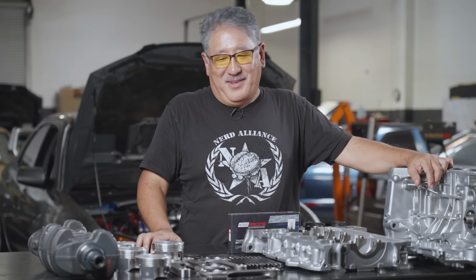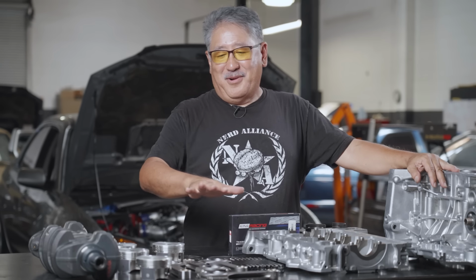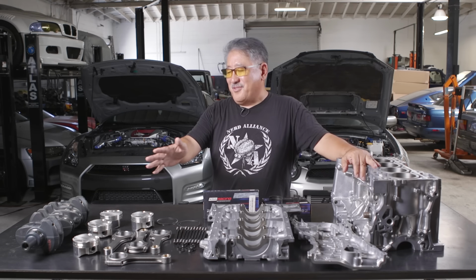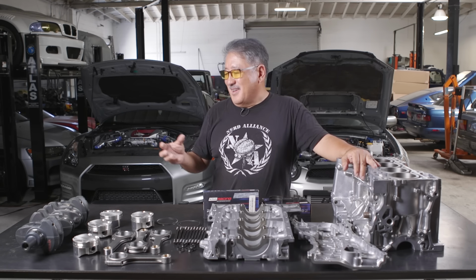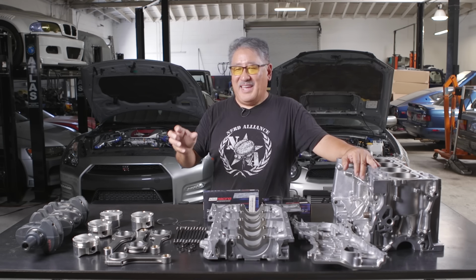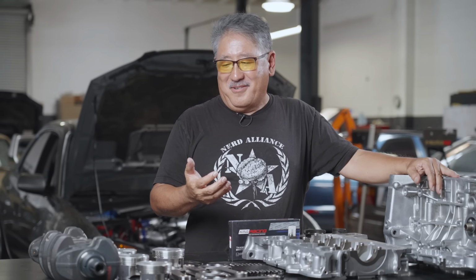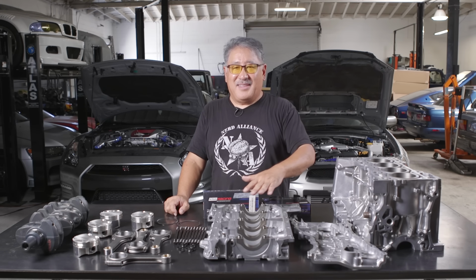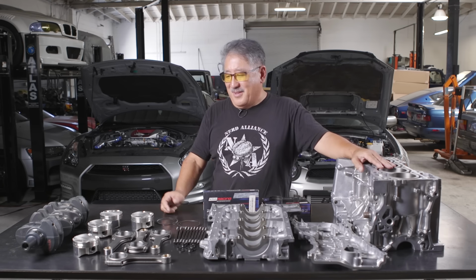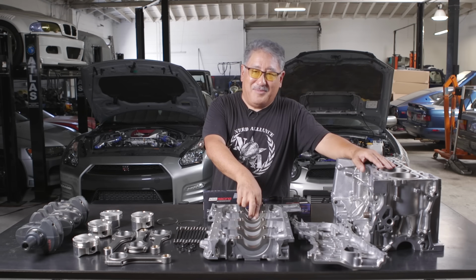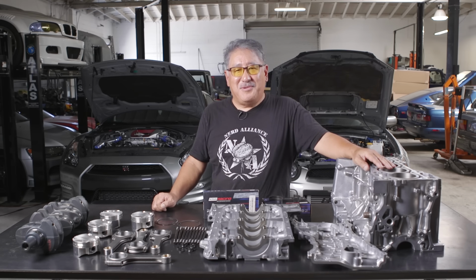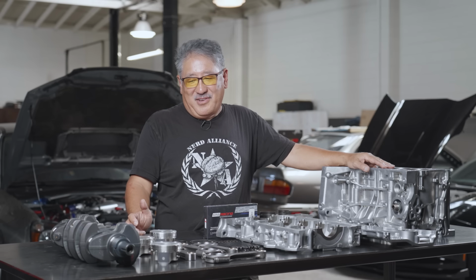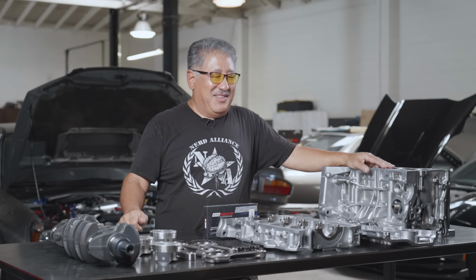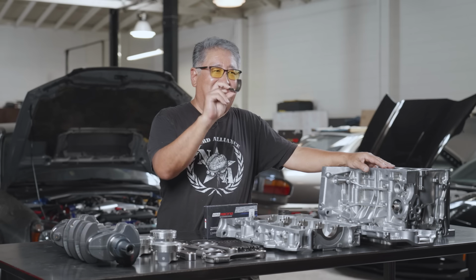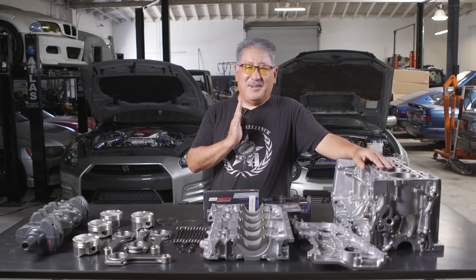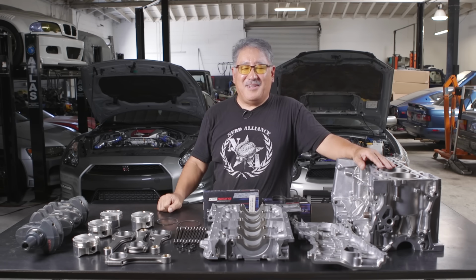Some of the tricks we do when we assemble an engine: the entire rotating assembly is balanced. We measure every single journal on the crank in several places. That way we know the true journal diameter, and if it has taper wear or if it's out of round or anything. Then we assemble the bottom end, bring it up to torque, and measure the bearing bores for the mains, so we know your true bearing clearance. We can adjust it a little bit by massaging the crank or the different bearing shells that we use. That way we get nice, consistent clearances for your bearings.